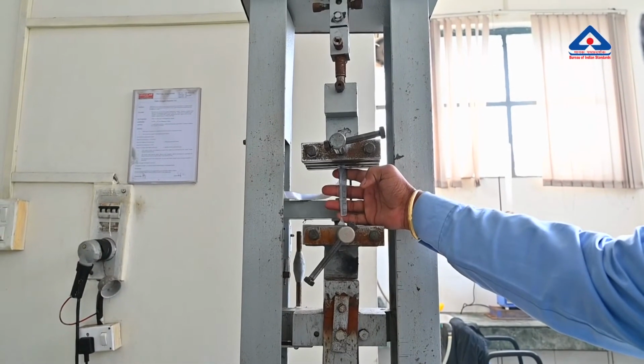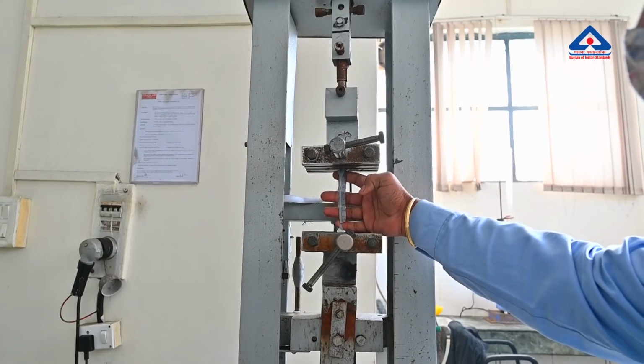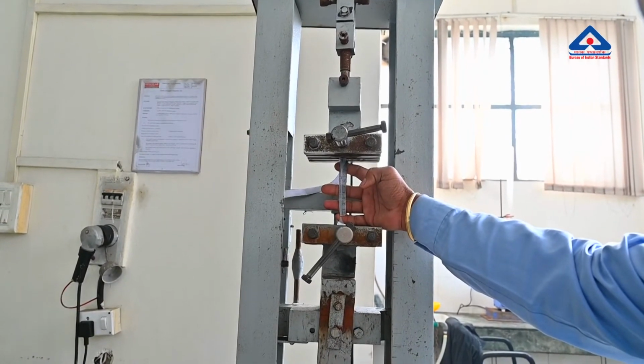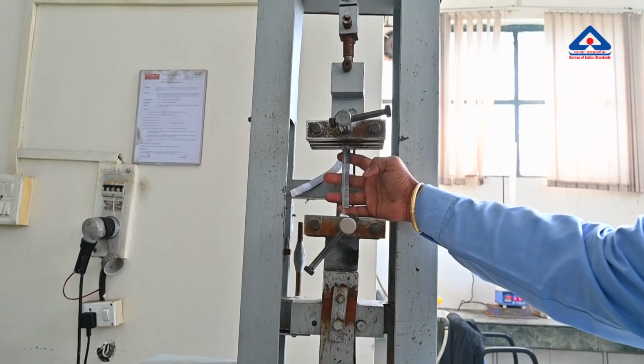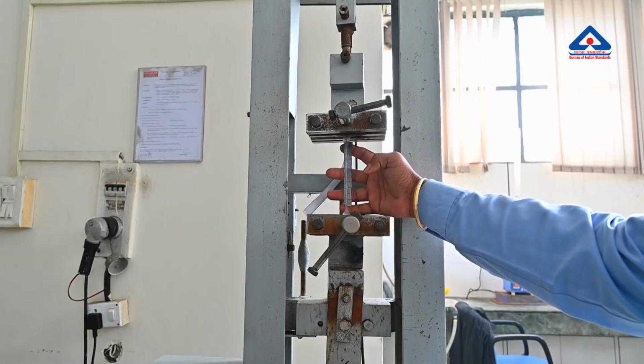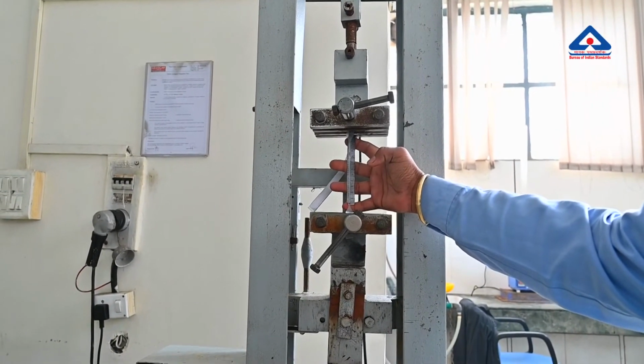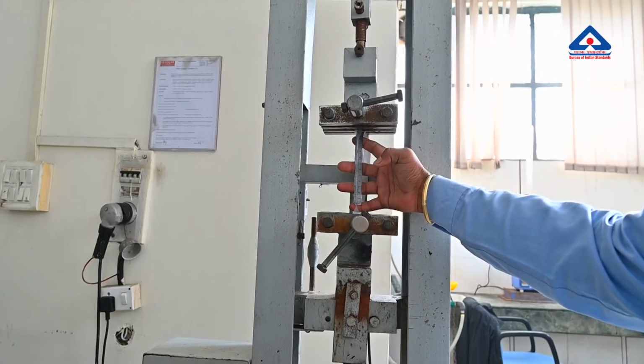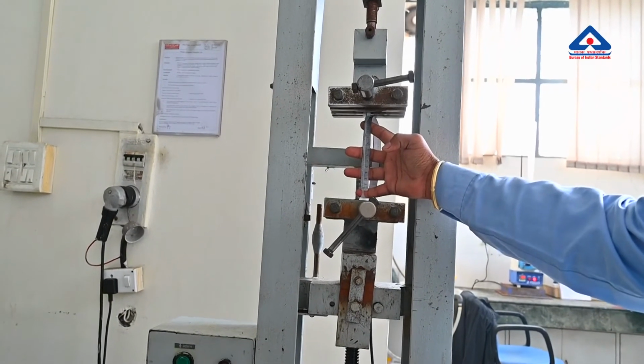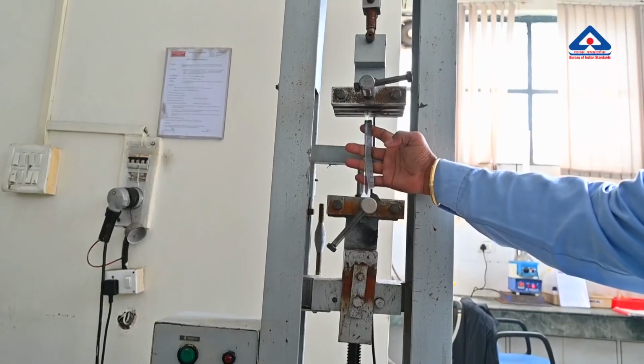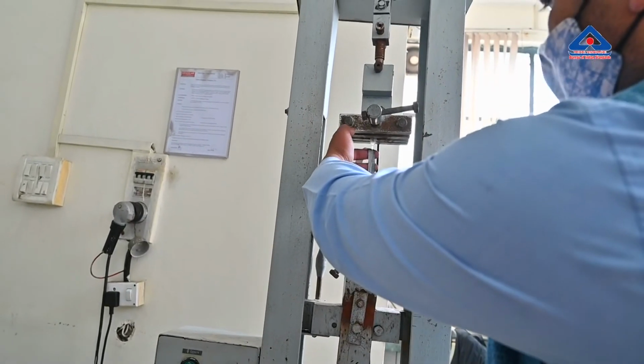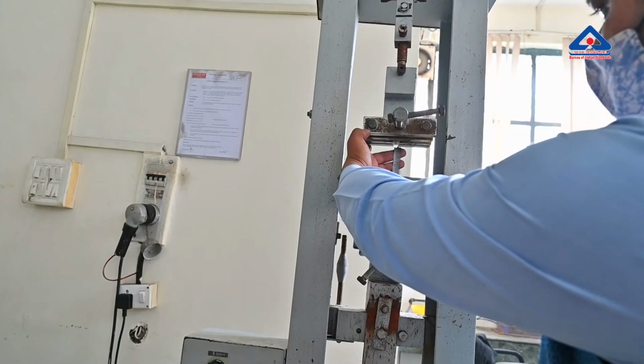Tensile testing is going on. For XLP insulation, as per the IS requirement, tensile strength is 12.5 Newton per mm square minimum, and elongation is 200% for XLP compound. After the breaking of the sample, we will measure the tensile strength as well as elongation. Now this test is in progress.